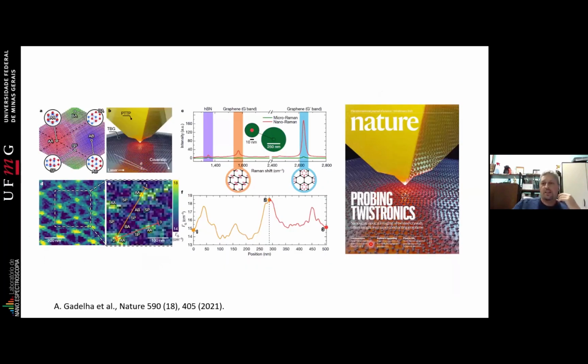This is just a kind of advertisement of how powerful and nice this technique can be. We measured twisted bilayer graphene, and we could see the crystallographic lattice of the twisted bilayer graphene with Raman, which was really amazing. And this was the cover of Nature two weeks ago, showing how this technique can make new things and open new paths.